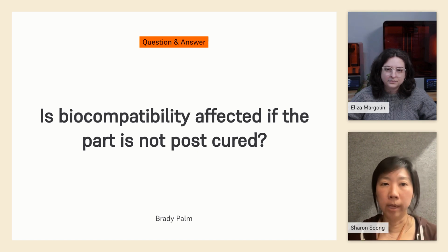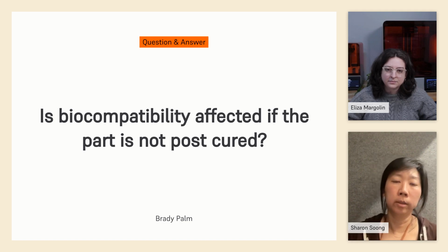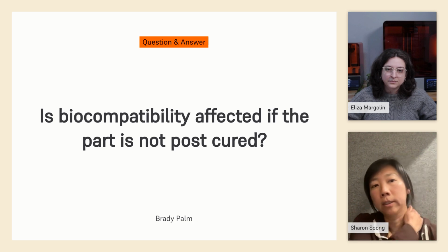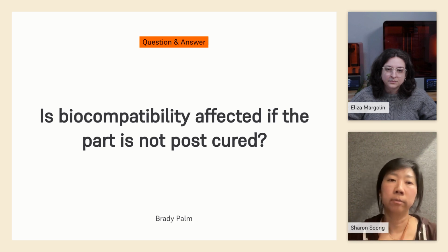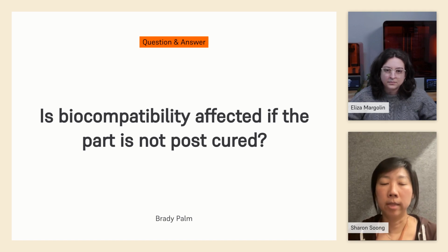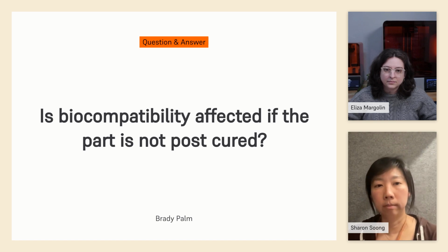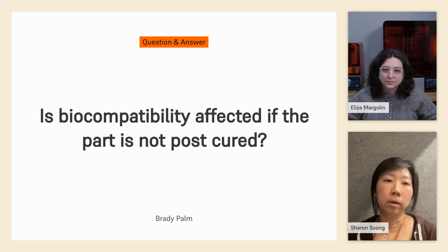This is because biocompatibility hinges a lot on how cured and how cross-linked your material is at the end. And as I talked about earlier, our polymer is not fully converted coming out of the printer. You can tell it's not, the stiffness will continue to increase as you go through the post-cure. And so you definitely want to follow our post-processing instructions, because then that would tie up all the loose monomers that could still linger around in your green parts, and those unconverted and cross-linked ingredients are often what will harm the biocompatibility of the part.